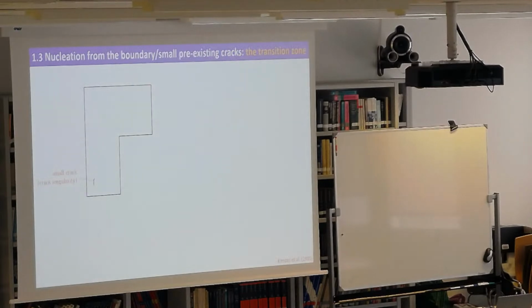All right. How about the transition zone? And this is where things experimentally are clear, theoretically not so much. So this is a typical experiment. People have done a lot of experiments with small cracks, right? This is essentially a plate with a crack of initial size indicated here and under tension. And this is the stress, the critical stress at which the crack goes. If the crack is large enough, Griffith will explain everything. If the crack is small enough, it seems to be the strength, but then you have a region that goes from one to the other, right? This is just one example.